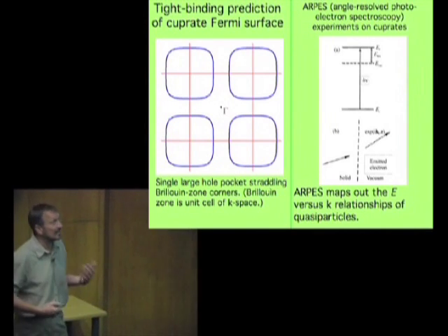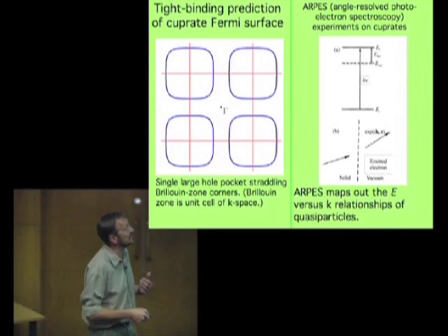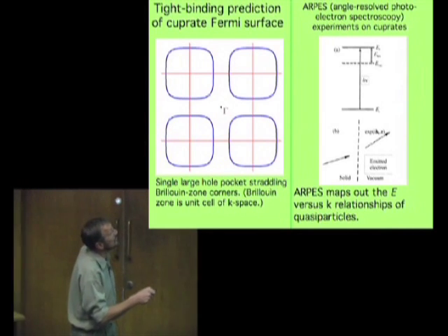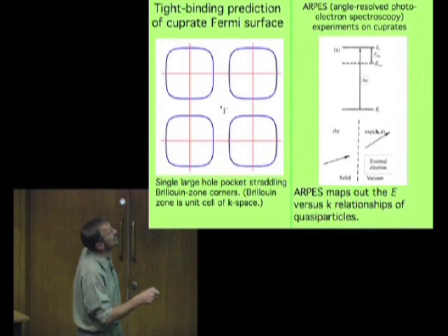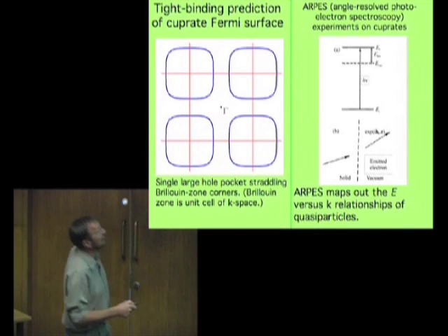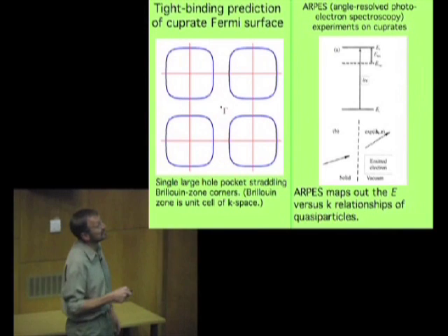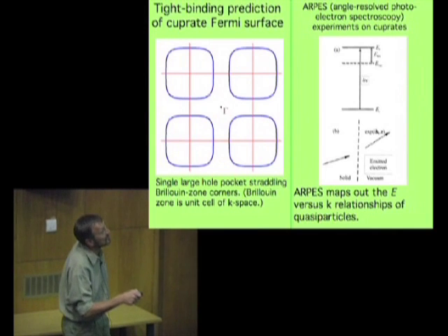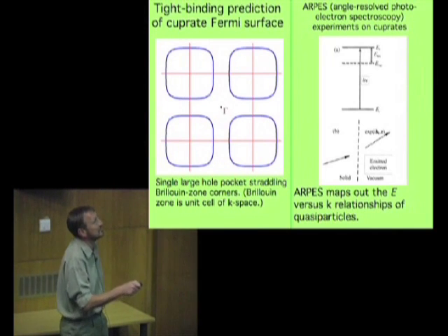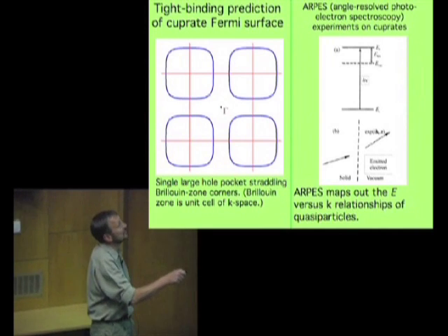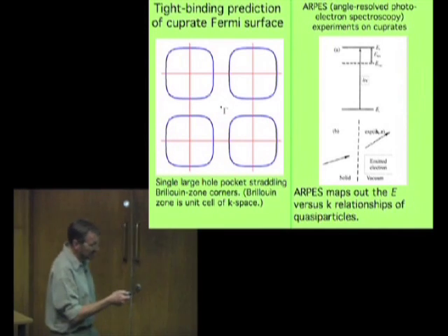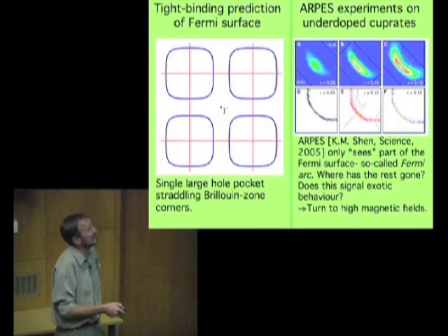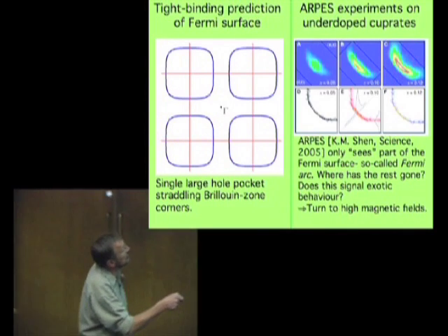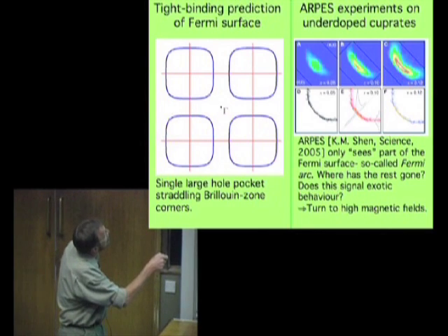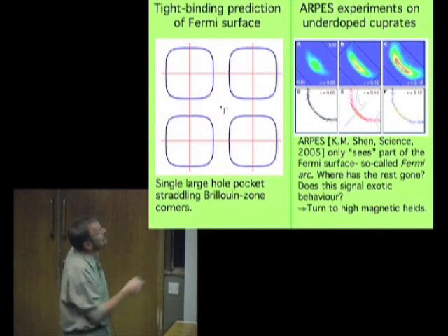Because a system like a crystal is periodic in real space, it's also periodic in K space. So if we get a Fermi surface here, we expect to see its replica at equivalent points in K space. So we have this Fermi surface that straddles the corner of the Brillouin zone, which is the unit cell of K space. We see replicas of it all around here. So in an ARPES experiment, we'd hope to map that out. So what the ARPES people do is they basically scan the wave vector of the electron along this region of the Fermi surface and hope to see it.